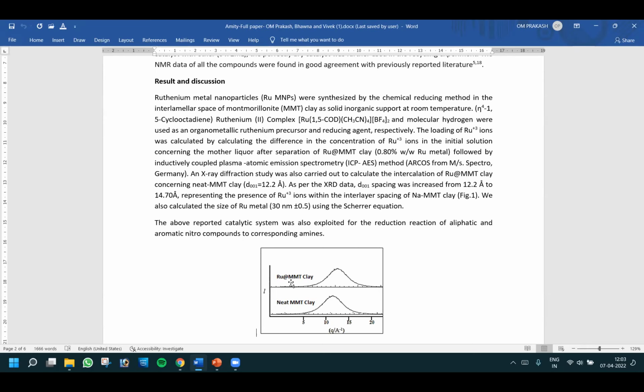As per the XRD data, the spacing increased from 12.2 angstrom to 14.70 angstrom, representing the presence of ruthenium ions within the interlayer space of sodium MMT clay, as shown here. We also calculated the size of the ruthenium particles, 30 nanometer plus or minus 0.5, using the Scherrer equation. The above reported catalytic system was also exploited for the reduction reaction of aliphatic and aromatic nitro compounds to the corresponding amines.